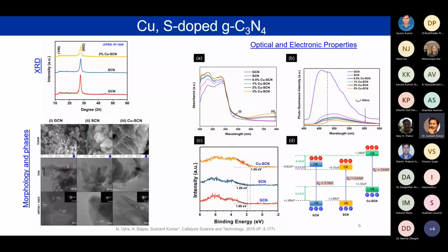So we did the valence band XPS, and here you can see that the copper SCN has shown 1.55 eV, and graphitic carbon nitride has shown 1.88 eV. Now, what does it mean? It means that once you have doped the copper and the sulfur in the graphitic carbon nitride, that has upshifted the valence band, and this is what you see here. There is an upshift of the valence band.